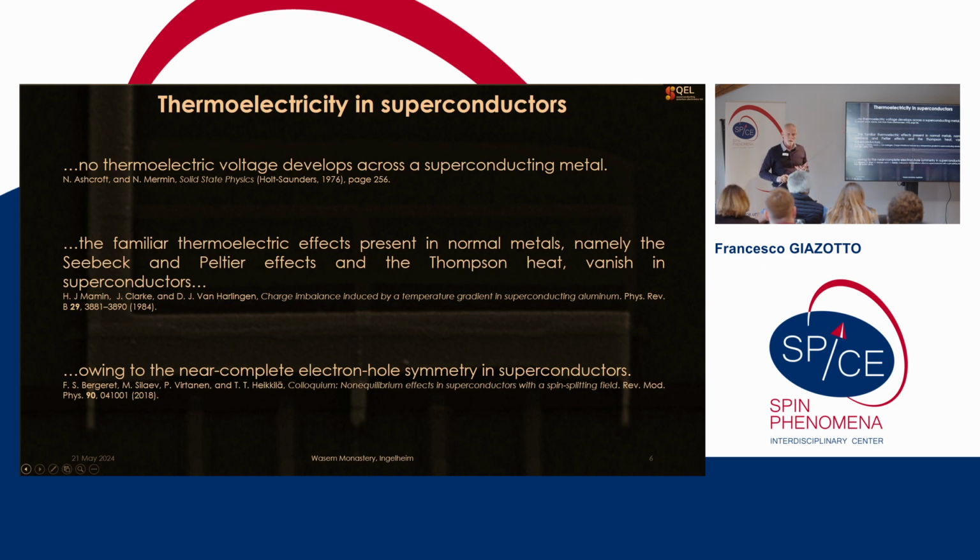To create power in a system, to manage the energy, indeed no thermoelectric voltage develops across the superconducting metal, thanks to this shunting by the supercurrent inside. What is interesting is that the familiar thermoelectric effects present in normal metals, namely the Seebeck and the Peltier, typically vanish in superconductors.